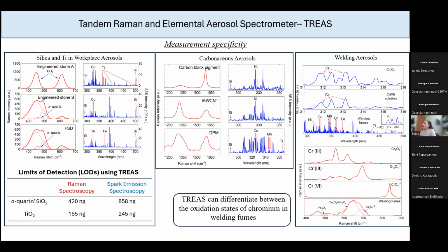First, we have the testing of some carbonaceous aerosols. When we apply Raman spectroscopy, we get the two characteristic peaks, the D and G peaks that we expect for the carbonaceous aerosols in all cases, like black carbon, multi-wall carbon nanotubes, and diesel particulate matter. But when we apply spark-emission spectroscopy, we cannot see carbon because it's outside of the detected range of the specific spectrometer. But we can see the presence of other elements, particularly in the case of diesel particulate matter, which has a lot more elements than carbon.